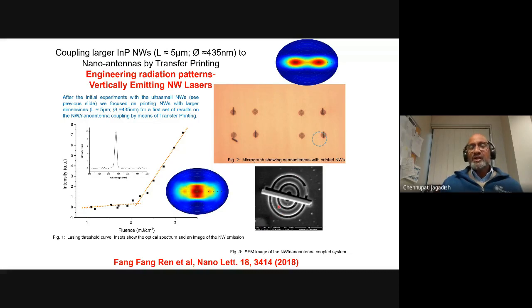Now if you excite this nanowire and look at the light emission, but you do not have any nano antenna, you get the light emission from both ends of the nanowire, because the nanowire acts like a fabricated cavity, which we talked about. Whereas if you have this nano antenna, light gets engineered, and suddenly you're getting the light from the vertical direction. Again, this work we published about two-plus years back. And again, you can see threshold-like behavior, sharp light emission, and now vertical emitting nanowire lasers. These are the world's first vertical emitting nanowire lasers. Again, it created a lot of excitement in the community here.